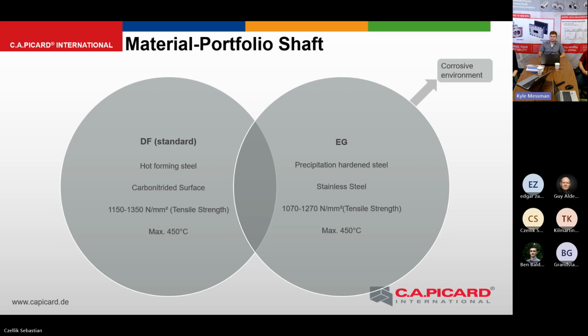And they have a tensile strength between 1150 and 1350 Newton per square millimeter. And you can use it up to 450 degrees. From the properties, EG is relatively similar, but this is a stainless steel which is precipitation hardened, and you can use it in corrosive environments. Some customers have very liquid products and it gets to the shaft and then they have a problem. And in the pet food industry, we use this material often because it's very hard to get the elements off when the shaft is rusted.